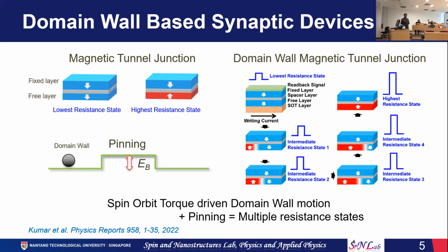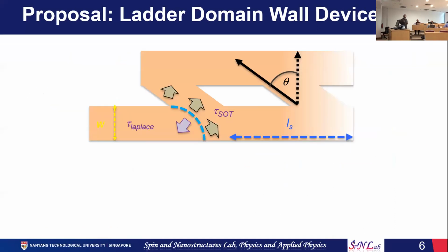So this is one thing, but the point is domain-wall motion is stochastic in nature. So we need to control its motion to achieve that. Different mechanisms have been proposed. It's called the pinning method. You can consider this domain wall as a ball moving on a smooth surface, and you are creating a surface energy barrier or energy well to stop this domain wall at a specific position. In this way, we can achieve these multiple resistance states.